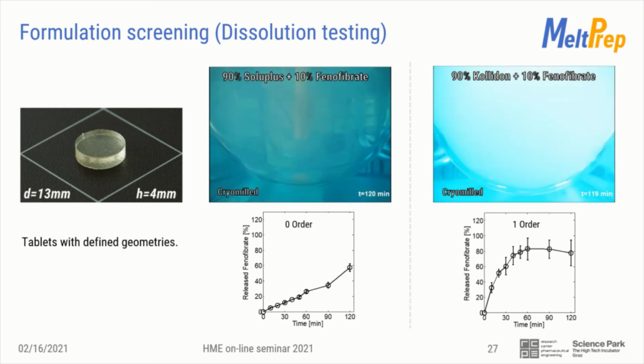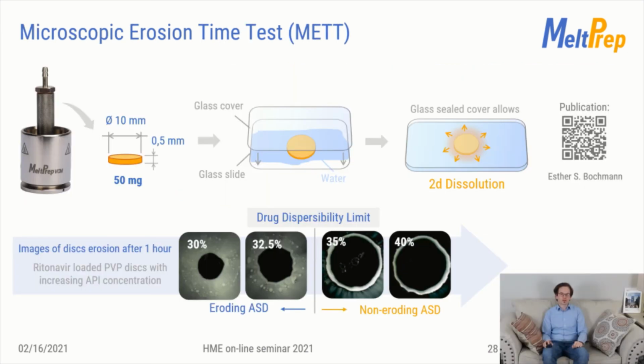Along the same lines, there was a publication released just before Christmas 2020 about microscopic erosion time testing from a group in Germany. It uses a microscope and a VCM sample that is embedded together within dissolution media between two cover glasses. Unlike the dissolution tester, they forced a two-dimensional stationary dissolution that allowed them to track the erosion under a microscope. By preparing multiple samples with various API content, their setup reveals the dispersibility limit of a carrier API combination with minimum effort.